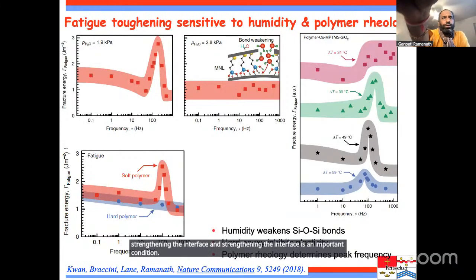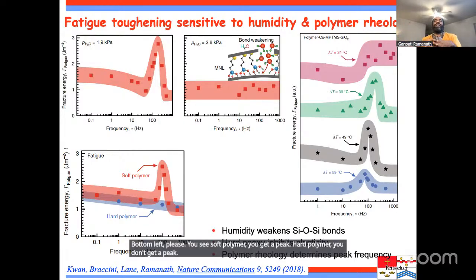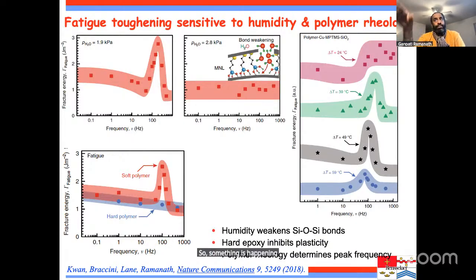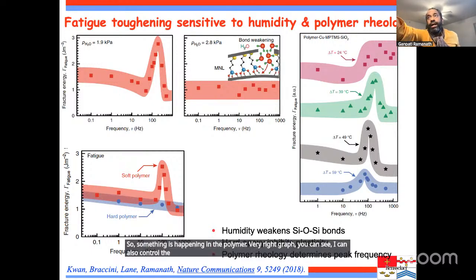Second thing that we did was, instead of using a hard polymer, we used a soft polymer, bottom left. Please, you see a soft polymer, you get a peak. Hard polymer, you don't get a peak. So something is happening in the polymer. In the bottom right graph, you can see I can also control the peak frequency. I can move it around if I change the temperature, which changes the polymer properties.